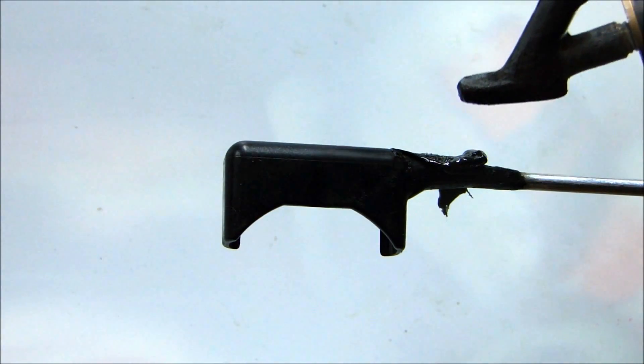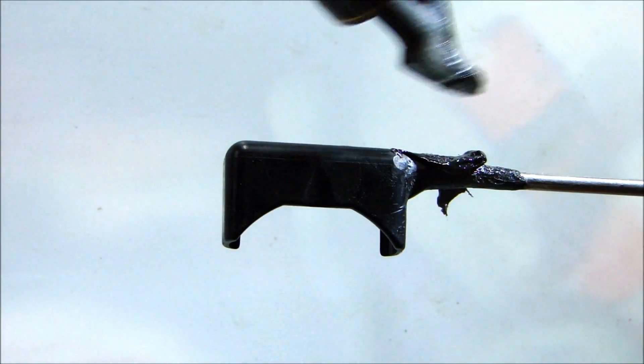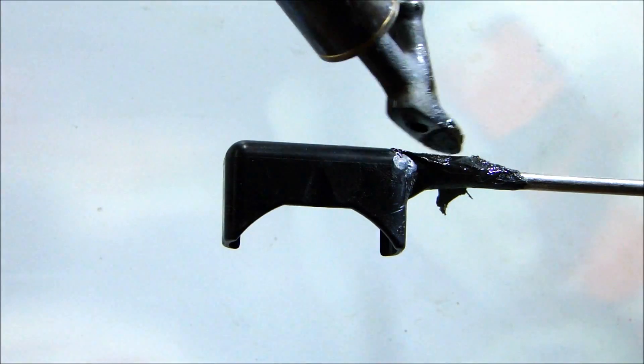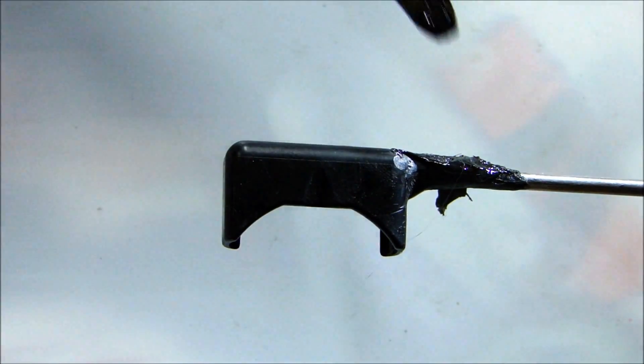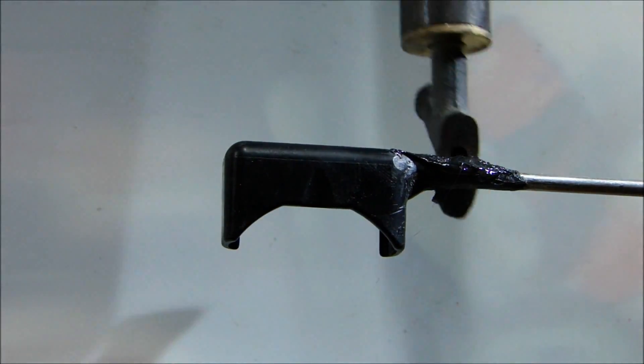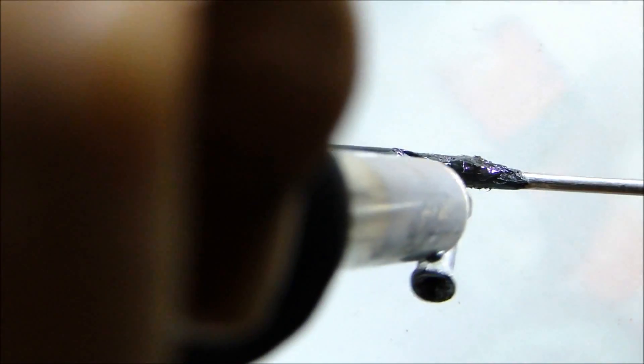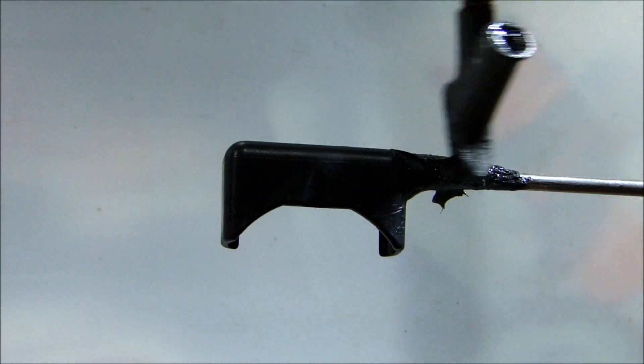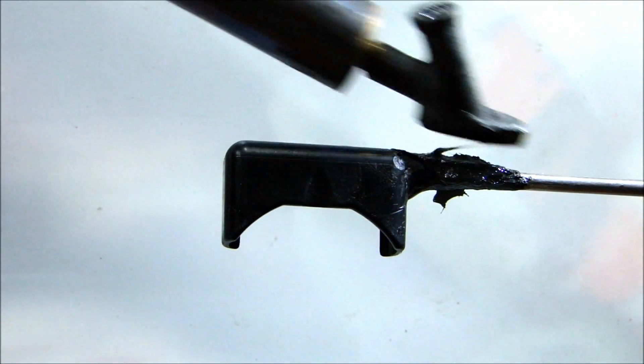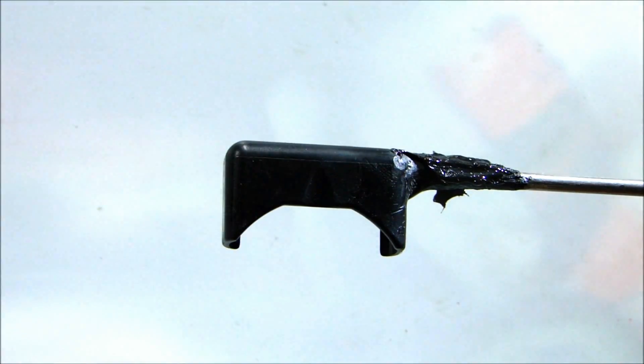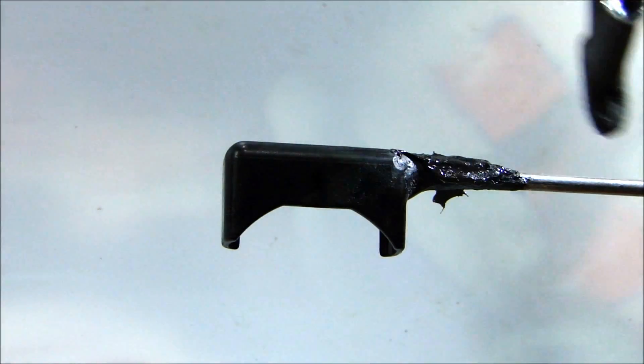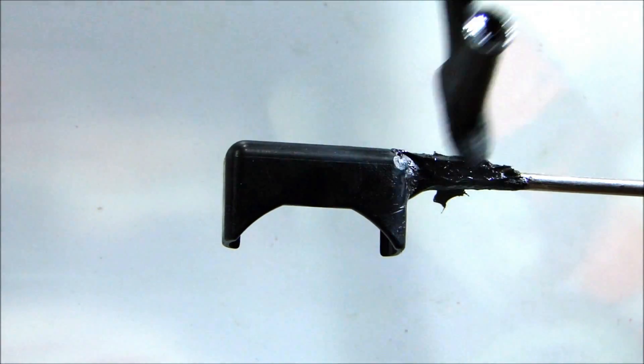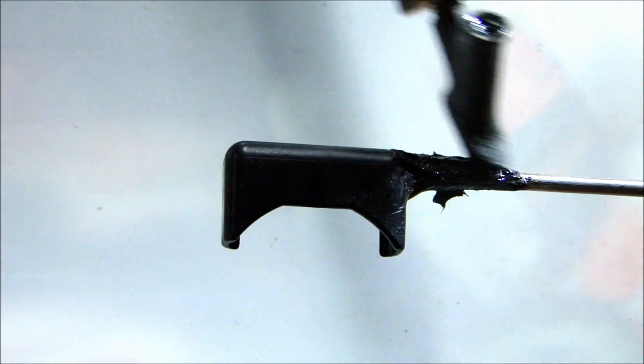I'm going to melt that, and I'm going to sort of pull this away and leave some of it underneath. Just like that. Weld it. Now you see, I have a bunch of plastic there that's left over from the rod, the filler rod I just pulled in. Now what I'm going to do is I'm going to take this, and very slowly and very gently, I'm going to take my iron, and I'm going to move it around to melt that filler rod. And since the Kevlar is in strands, I'm going to go in straight directions so that the Kevlar strands don't get all crooked and I lose the strength. Because Kevlar is in straight lines, just like the Kevlar cloth. It's woven into a cloth, and when it's straight is when it's the strongest.